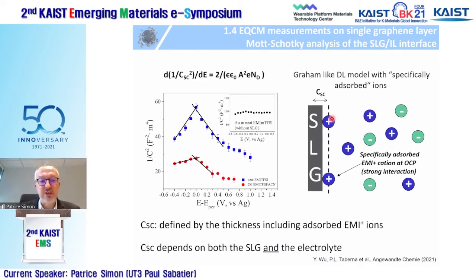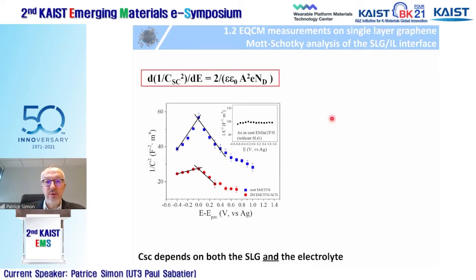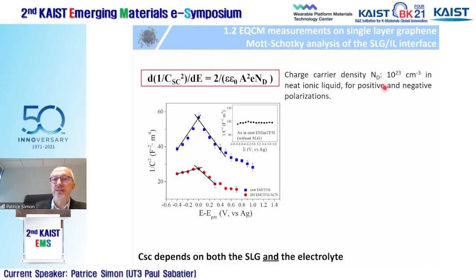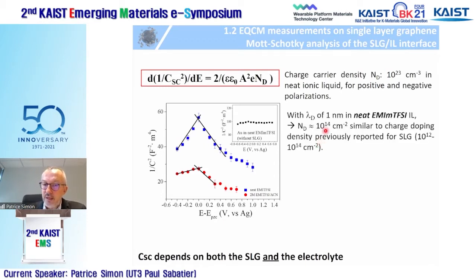So in fact, this space charge capacitance depends on both the single graphene and the electrolyte. And if you do a kind of analysis of the charge carrier density, we found a charge carrier density of 10 to the power 23 per cubic centimeter in neat ionic liquids for both polarizations, which is given by the slope here. And if you consider a Debye length of 1 nanometer, meaning that the charge separation, including the strongly adsorbed cation, is 1 nanometer, then you end up with 10 to the 14 charge carriers per square centimeter, which is very much in line with previously reported results.